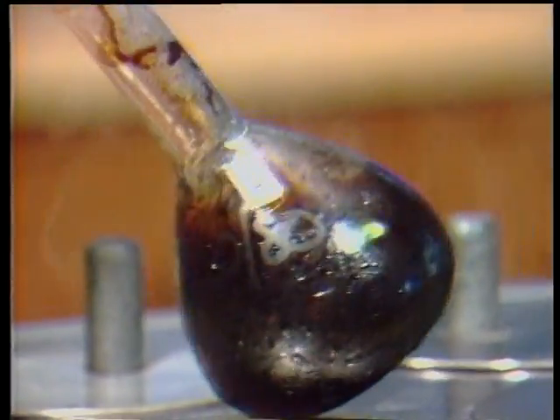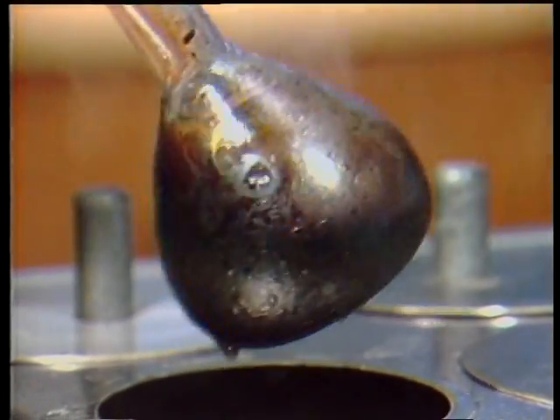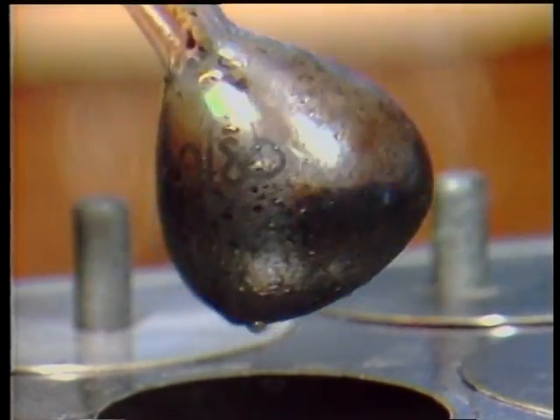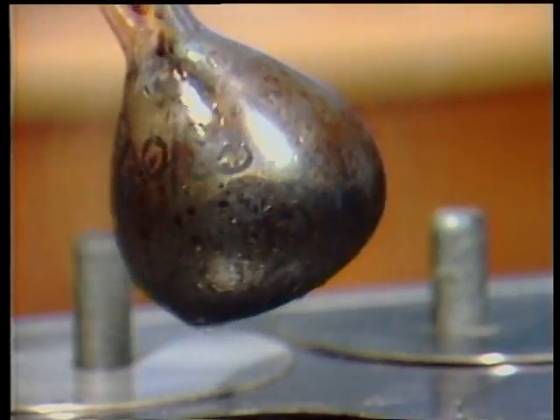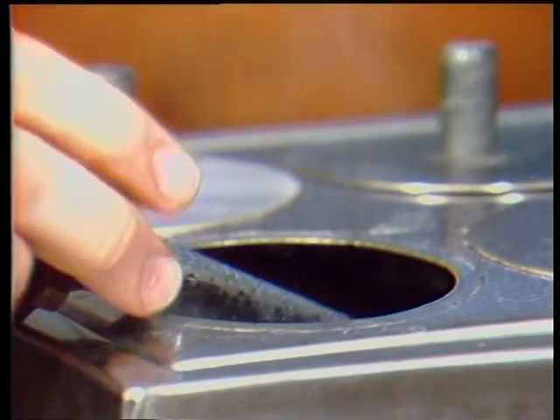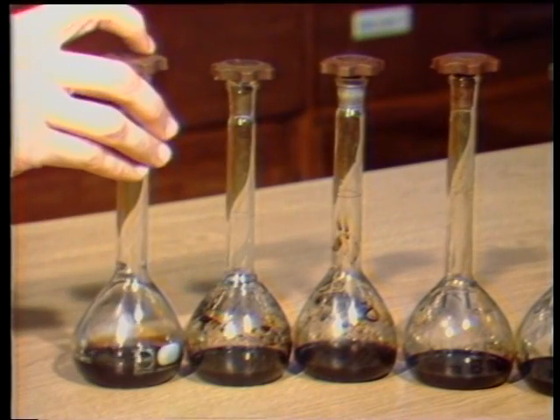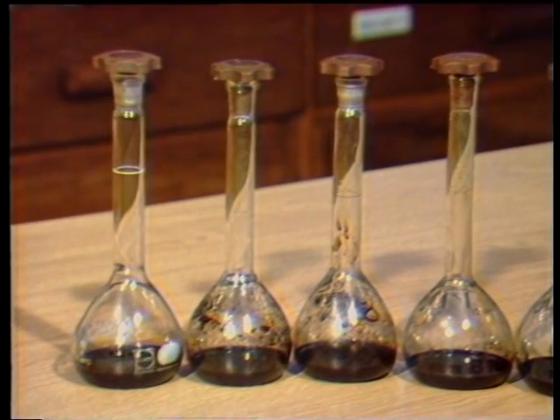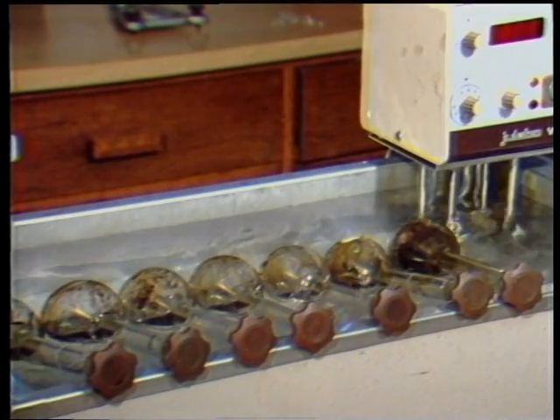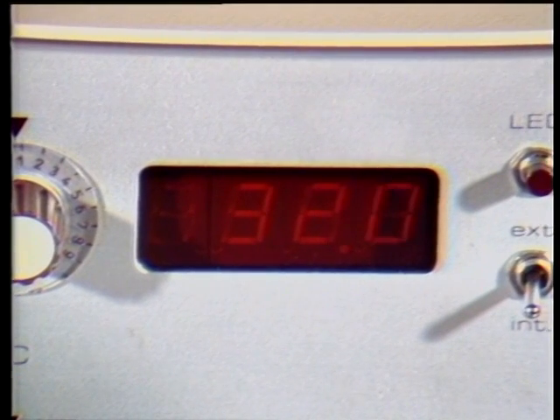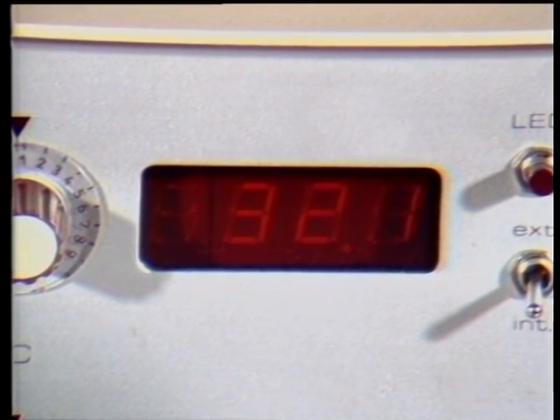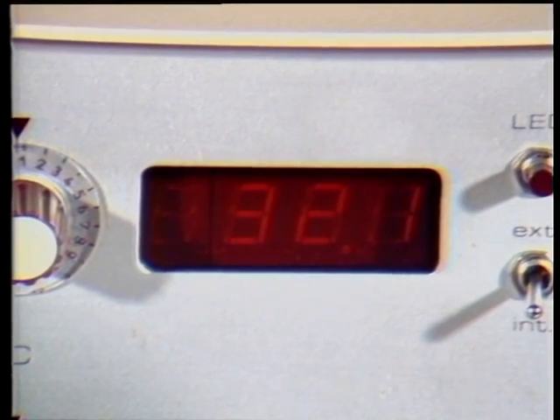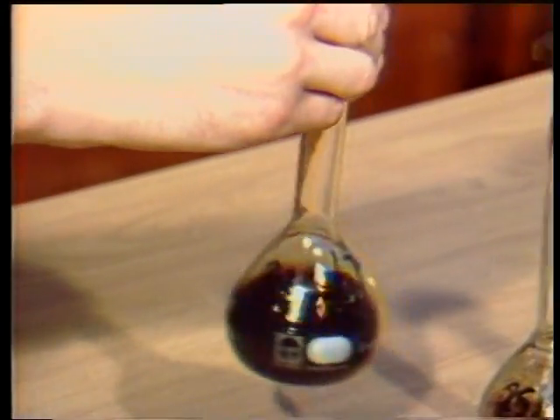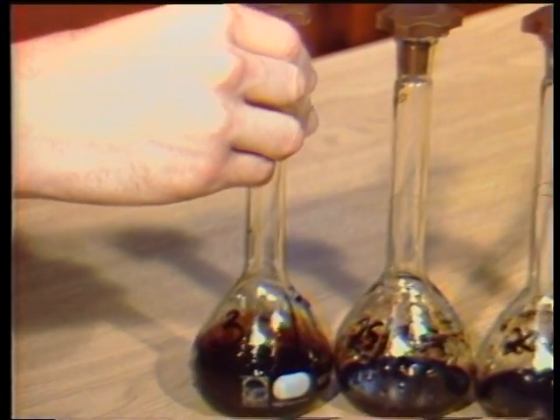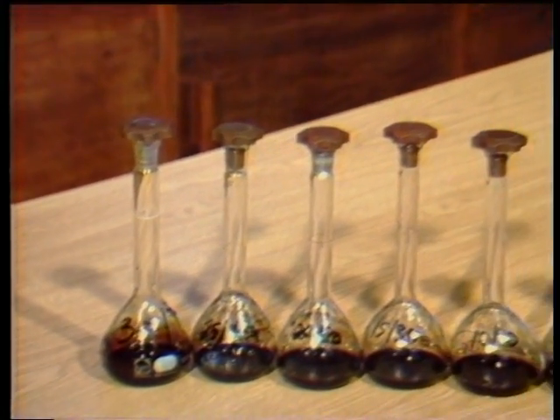Remove each flask, shake and rotate it to ensure mixing, and replace in the water bath. Repeat this procedure for 8 minutes. Remove the flasks and allow them to cool at room temperature for half an hour. Place the flasks in a water bath at 32 degrees Celsius to the nearest half a degree for 15 minutes. Remove the samples, swirl, and place them in an order of descending xylene content.